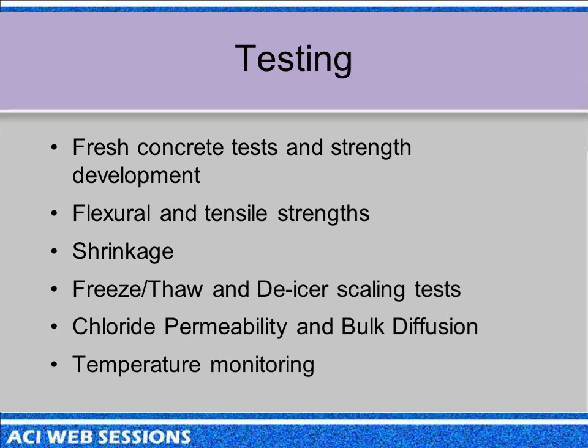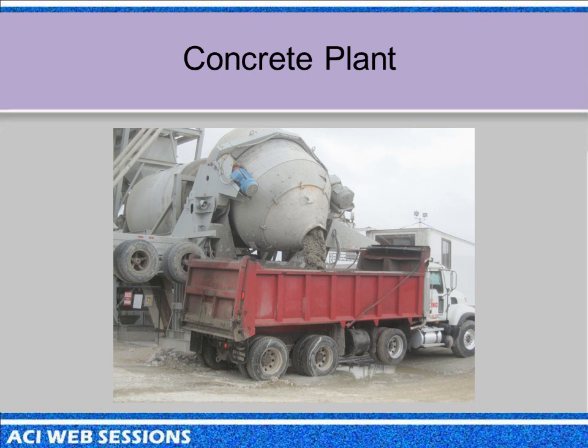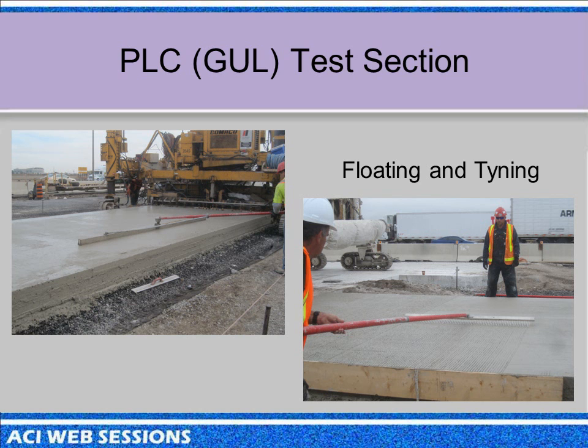And I don't have a lot of data for this because the 28 days was actually yesterday, and I haven't got the 28-day data, but I'll show you the 7-day data. Fresh tests we did. We're doing flexure and tensile because it's pavements, shrinkage, freeze thaw, and de-icer tests, chloride permeability, and chloride bulk diffusion, and we did temperature monitoring. And these were done in a premix plant set up for the paving operation, delivered in dump trucks to the site, put into the paving machine, and slip formed out of the paver, just showing here, doing a bull floating, and then here tining. Because it was only 1 lane wide, they didn't use the tining machine, they just did it by hand.